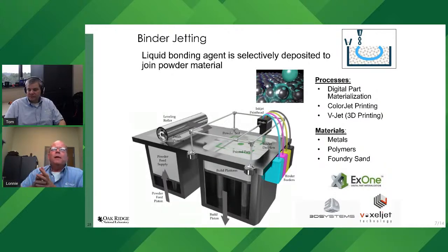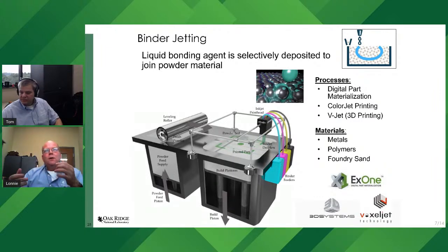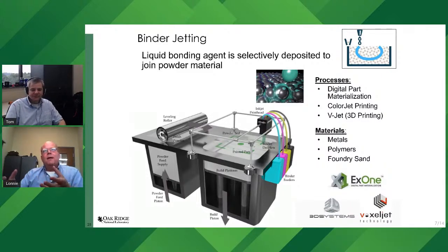HP, ExOne has been making these systems for probably 20 years. In terms of industry, this one actually is used a lot for sand casting. There's companies that make jewelry with it. Of all of the processes, it's probably the least expensive of all the metal additive processes, but it still has a lot of steps. So you're using a binder, you're gluing these particles together. When it's done, again, you'll have technicians that are like archaeologists with brushes, carefully removing the part that's embedded in this powder bed.